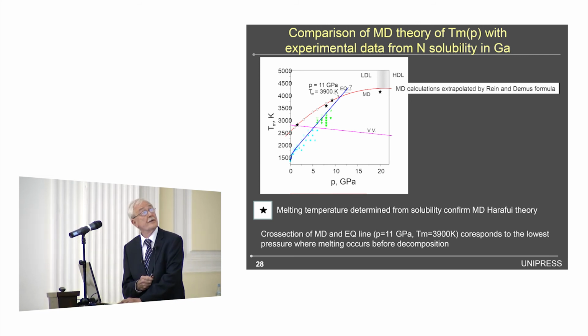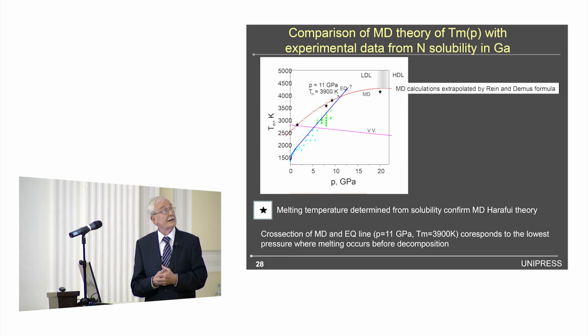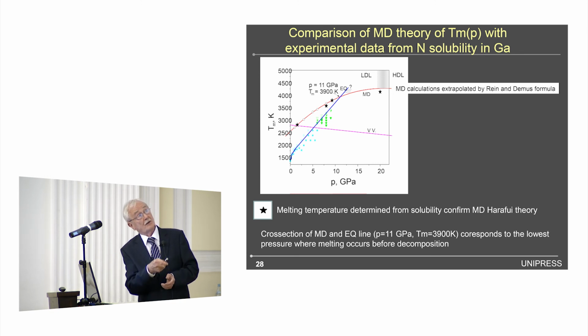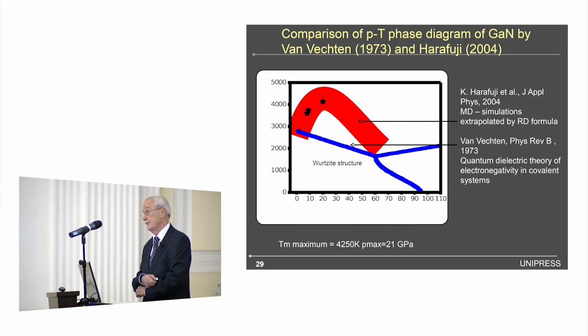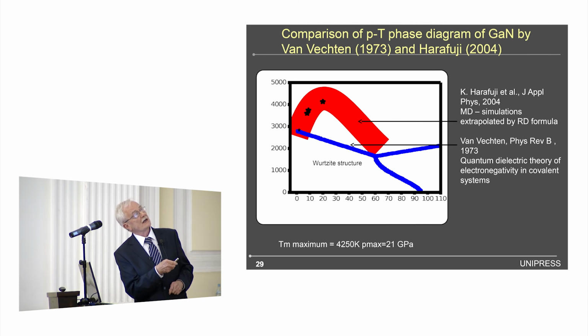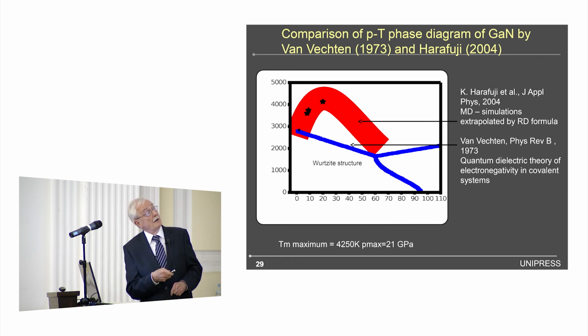And we did one more thing. Using this RD formula, Rein and Demus formula, which I showed already, we extrapolated it further, and you have this diagram here. These are calculations by Van Vechten, and that's Harafuji molecular dynamics extrapolated data. These are our points. These are 3 points which are here. The maximum temperature corresponds to 4,250, and it's at 21 gigapascals.